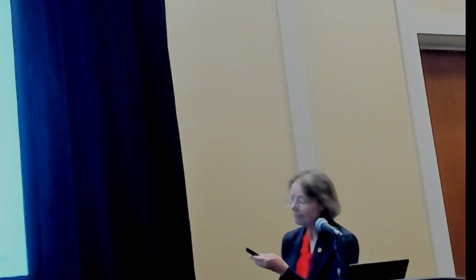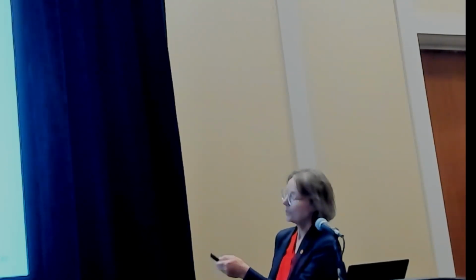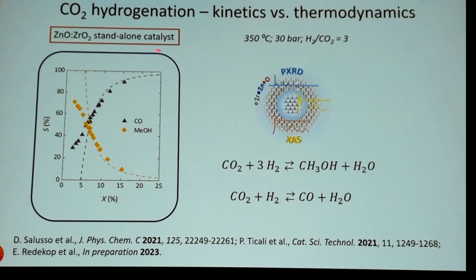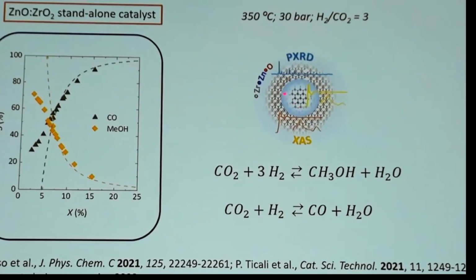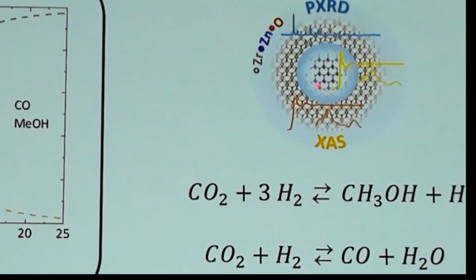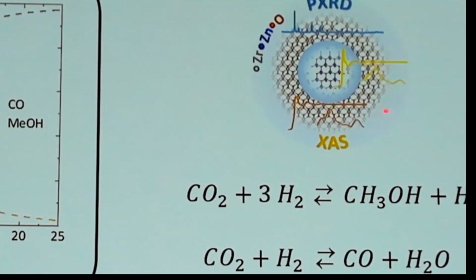Okay, so let's go now to the co-feed studies, the CO2 hydrogenation. We start with the standalone methanol-forming catalyst, zinc oxide zirconia. And this is a catalyst where you have detailed PXRD and XAS studies. They have shown that the catalyst consists of small clusters of zinc oxide distributed in zirconia, and the reaction is happening at the interface between these two phases.